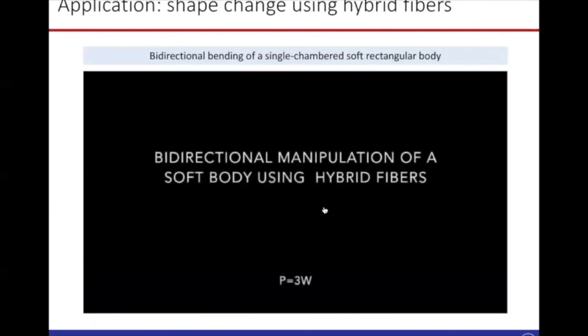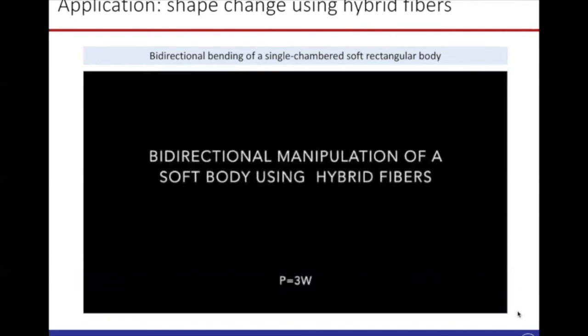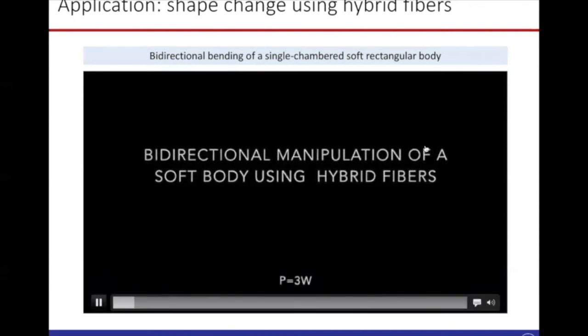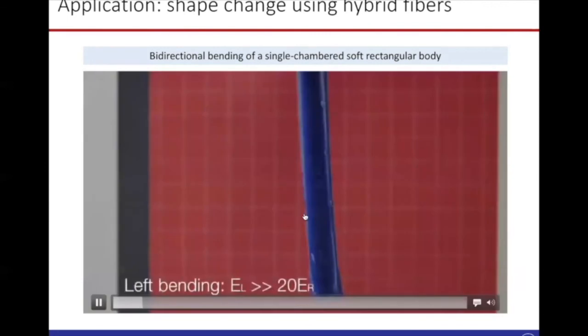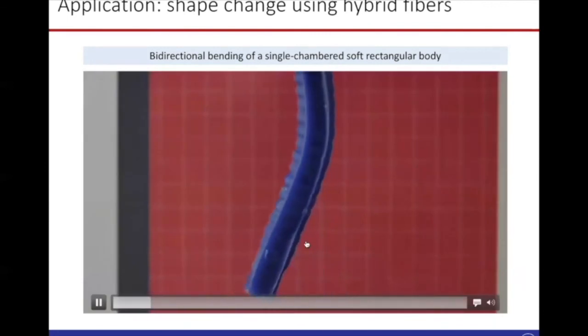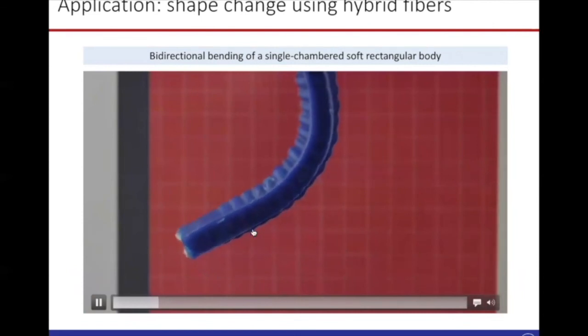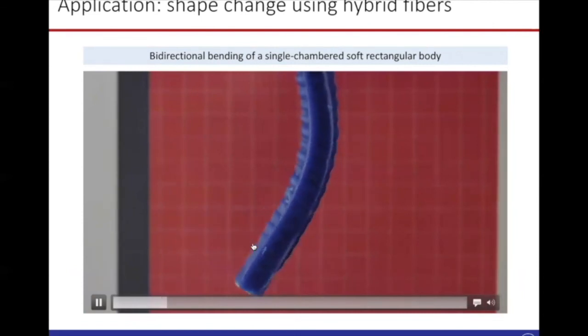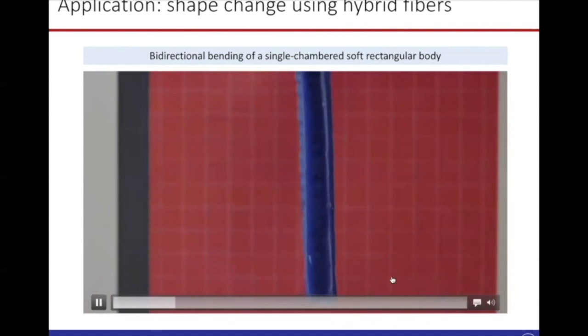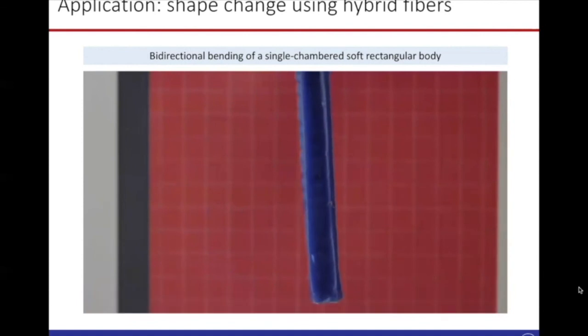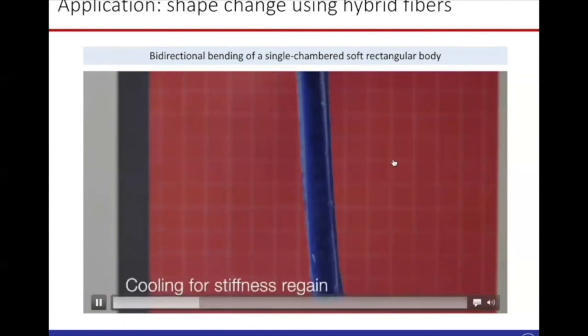And here we show a bidirectional bending. So we use a single chamber actuator, and we have a set of fiber integrated on left and right side. Then you unlock the fiber on the right side. Here the fiber is locked, and then you can bend it to one direction. Then you revert this actuator back to its initial position, and then you cool the gallium to regain the stiffness of that fiber on the right side. Stiffness regain takes 1 to 2 minutes, so I'm just speeding up.